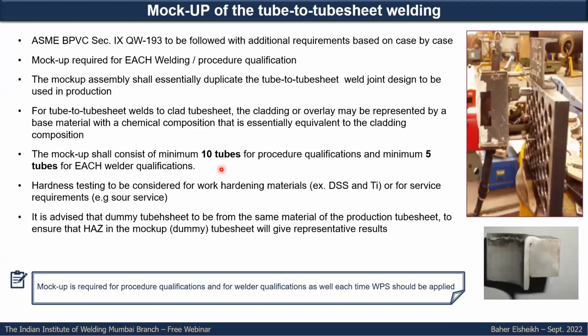One thing you need to think about while selecting the material for the mock-up for the tube sheet: in many cases they are using tube sheet from similar material, not exactly the material used in the application or the production. This might give some misleading results, especially if you have improper properties or quality of the heat affected zone in the tube sheet side. If you have in the mock-up the tube sheet side weld heat affected zone with some higher hardness, or some issues in the microstructure or the grain size, and you are not using the same material for the production, you cannot rely on the results. You will not be able to reject it.